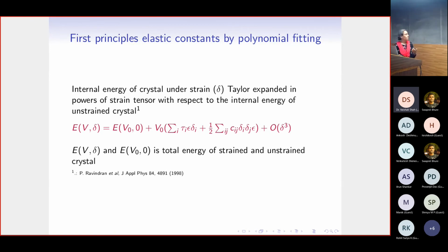So we followed an alternate method. In this alternate method, the crystal structure is put under a strain, and we do a Taylor expansion, and by following the Taylor expanded polynomial, we fit for the elastic constants. So we know this is the energy of the system without any strain. This will be the energy of the system with the strain we have applied. We vary delta, so we know the amount of strain we have applied, and so we can compare the energy of the strained and the unstrained crystal, and by doing this for various values of delta, we do a fitting, and we are able to obtain the elastic constants for whichever elastic constant one is interested in.